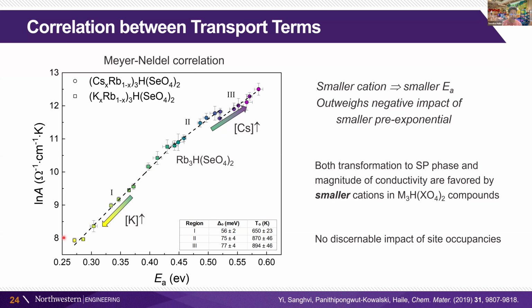And it has been somewhat explained by saying that if you're trying to get over an activation barrier for conductivity, if you have a higher vibrational state, and more vibrations, you're higher up in the energy potential well. So therefore, the more vibrational entropy you have, effectively the smaller the barrier, even though the energy landscape may be the same. You're starting at a higher position because of that vibrational entropy. And that would be the explanation for the correlation between these two. I would say this is still very much an open discussion, but that is one potential explanation for why these two parameters are scaled together.